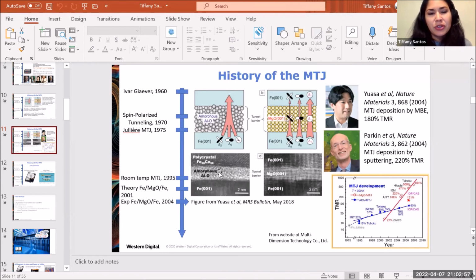Now, for example, if you do amorphous aluminum oxide and iron electrodes on top and bottom, at most you get a spin polarization of the iron at best 50%, so you'll never reach several 100% TMR with that. Whereas with the MgO barrier, you can get nearly complete polarization of the iron in the tunneling process. So that would be P close to 100%.